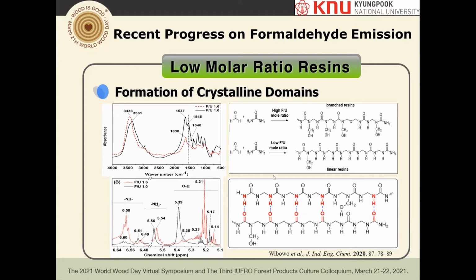And then we came up with ideas like this. The high molar ratio resins are like this, a little bit of branched polymers, but when you have a low molar ratio, it's pretty much linear molecules because the formaldehyde is kind of the cross-linker. Less formaldehyde means less cross-linkers. So what I thought is we have this kind of hydrogen bond between linear molecules, from the amino group NH to the carbonyl groups. This is consistent with FTIR and proton NMR.